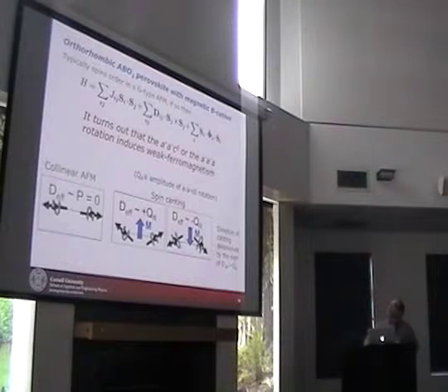But a rotation will. In fact, rotations that we talked about before in these perovskites completely determine the sign. One particular rotation completely determines the sign of this interaction. If the rotation rotates, say, in a leftward sense, the sign is one way. If it rotates in the other sense, the sign is the other way.